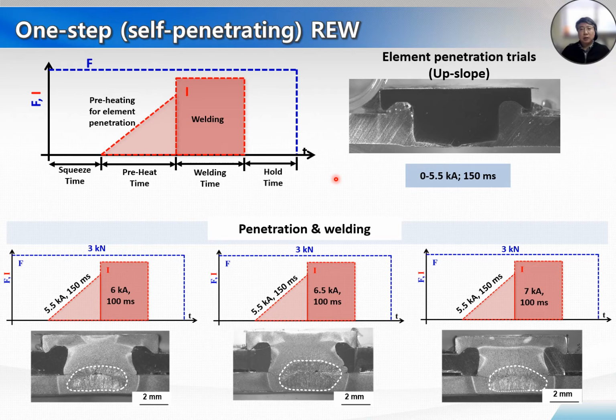We applied the current profile of the preheating step using current upslope, which is suggested in various literatures, and constant current was applied in main welding to secure a successful fastening. In particular, when the main welding current increased, the nugget size of the resistance welding area increased and joint strength also dramatically increased.